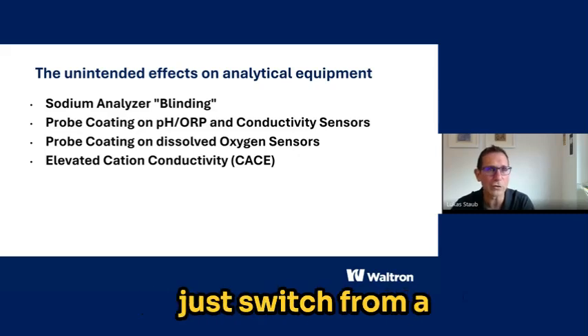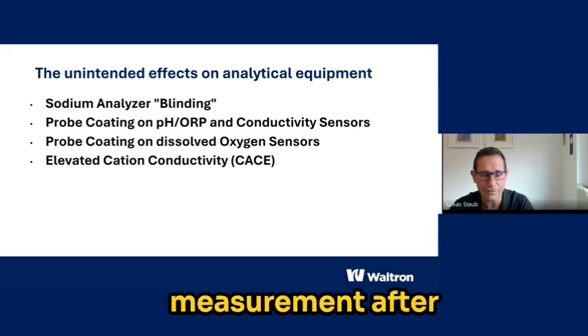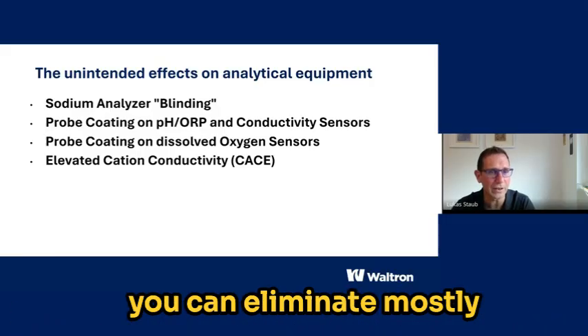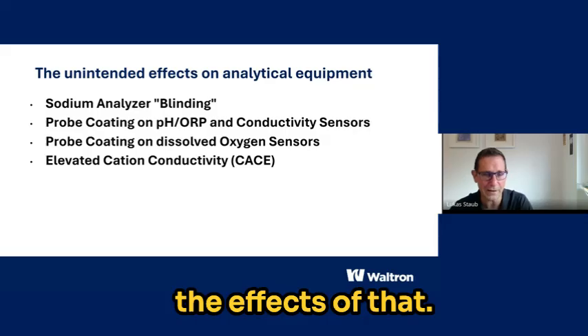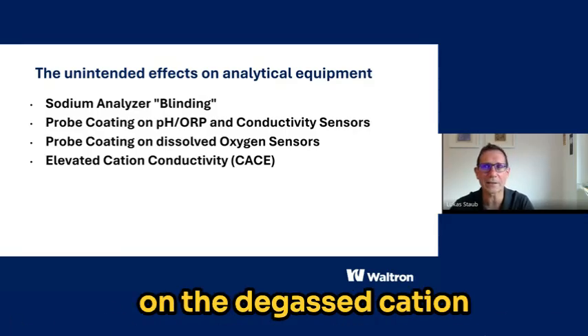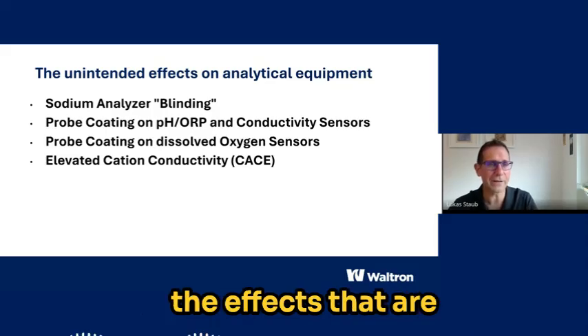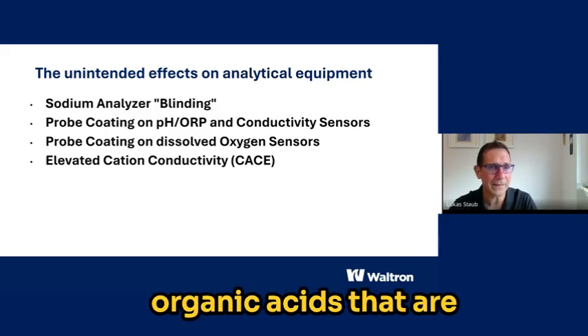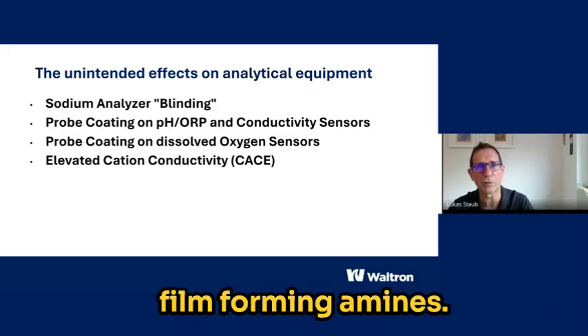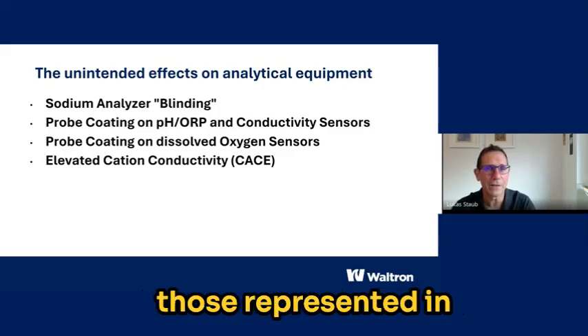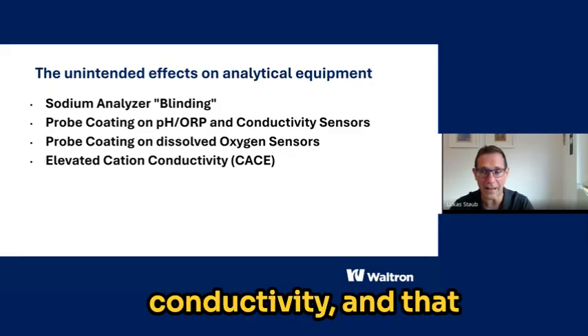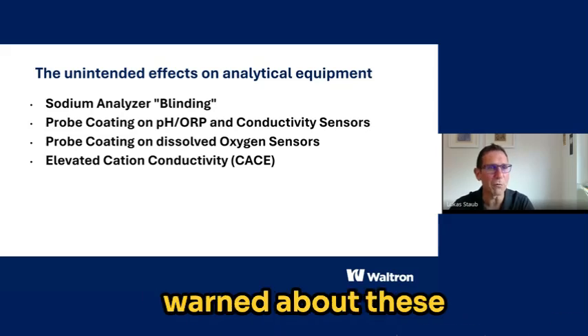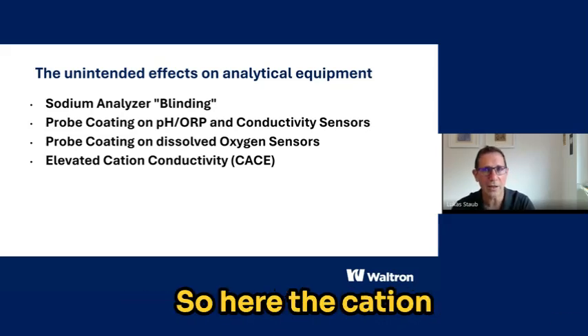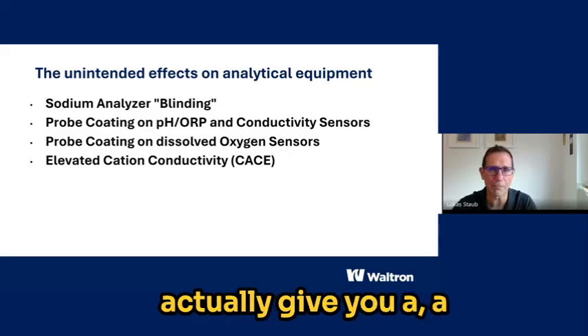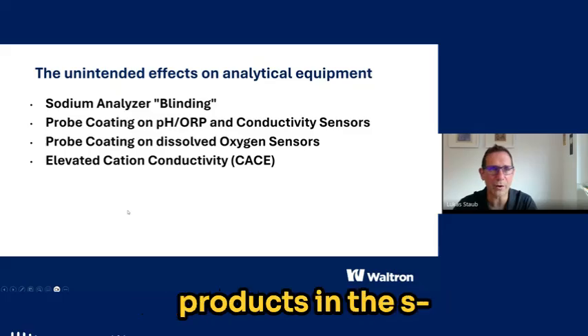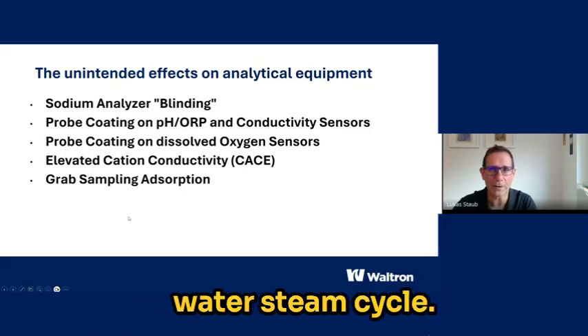You will probably just switch from a standard conductivity measurement after cation exchange to a degassed version, and you can eliminate mostly the effects of that. What will still be seen on the degassed cation conductivity is actually the effects that are coming from these organic acids that are also decomposition byproducts of these film-forming amines. So you will actually see those represented in the degassed cation conductivity, and that is a good thing to have because you want to be warned about these decomposition products. So here the cation conductivity will actually give you a pretty good indication if there are decomposition products in the water steam cycle.